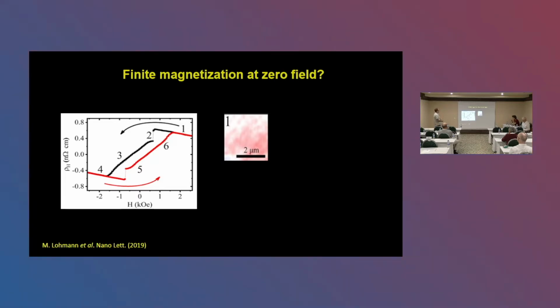And what people have seen, other groups, was that you get a small but finite anomalous Hall effect at zero field. They've also managed to do MFM at the same time. When the sample is fully magnetized, you see almost no features on the image.